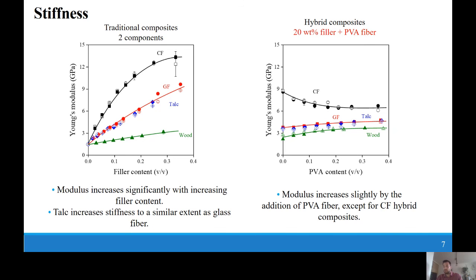In the case of hybrid composites, right side, the stiffness increases slightly with the PVA fiber content, except in the case of carbon fiber composites, where the debonding of the polymer fibers is assumed even at small deformations. Furthermore, it can be seen in the figure that the effect of the coupling agent is negligible.